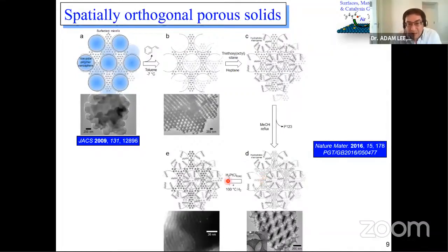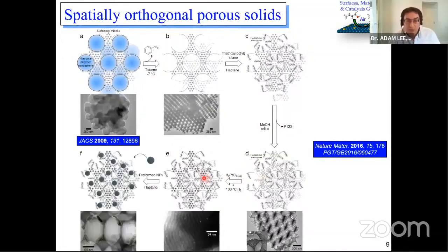So a platinum aqueous precursor, for example, will go only into the small pores because they are hydrophilic, whereas a larger nanoparticle of palladium, which has some organic ligands around it to stabilize it, will only go into the hydrophobic cavities, the large pores. So we've managed to achieve selective patterning and compartmentalization of platinum nanoparticles in the small pores and palladium nanoparticles in the big pores.